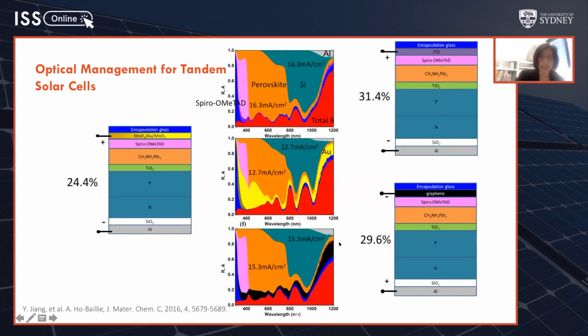And the idea is to look at what the other layers are absorbing, parasitically we call it, because these layers are not responsible for electron hole pair generation. They're actually stealing light from the perovskite or from the silicon. So we want to find out how much light is being absorbed. For example, this gold layer is very absorptive and we don't like it. We also want to look at the total reflection, which is represented by the red. So the smaller the red area, the better.